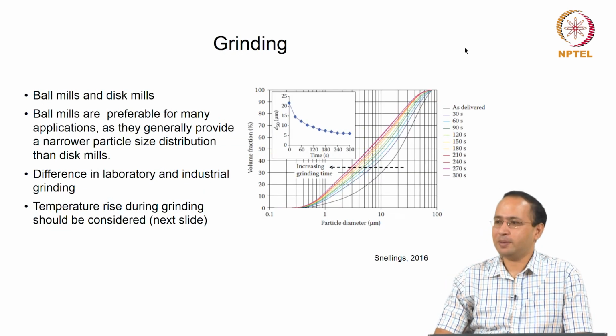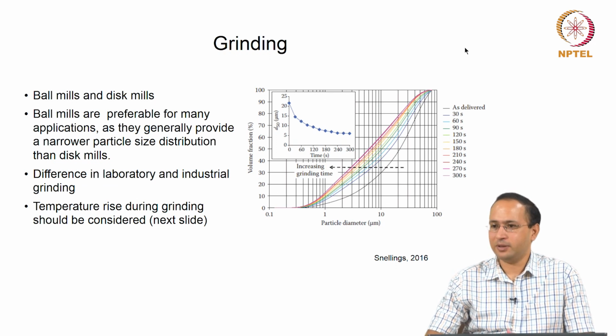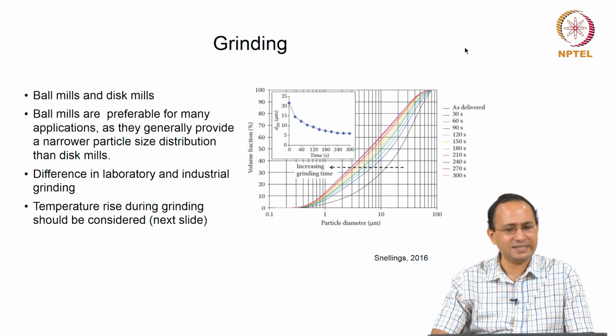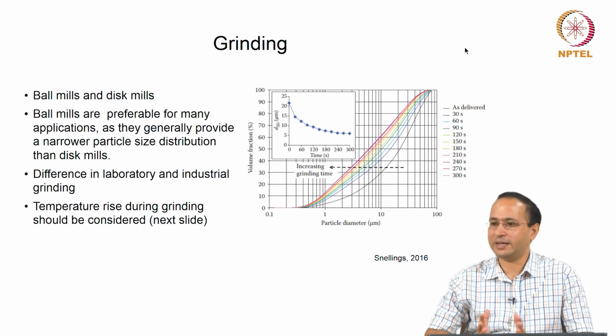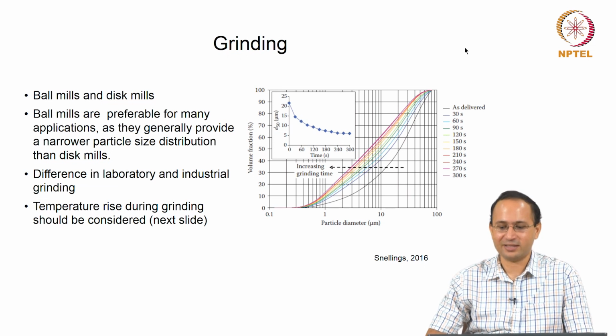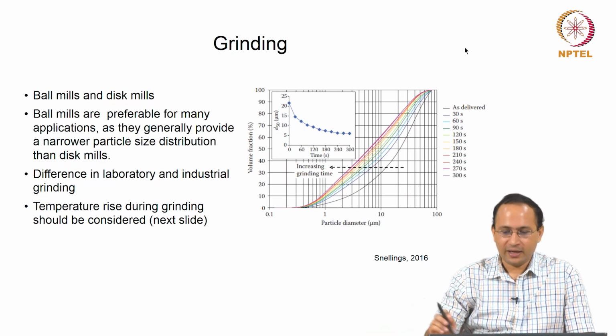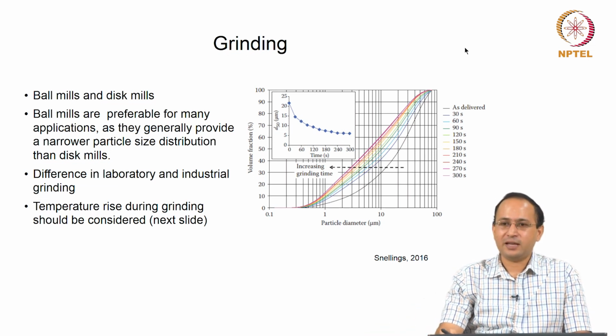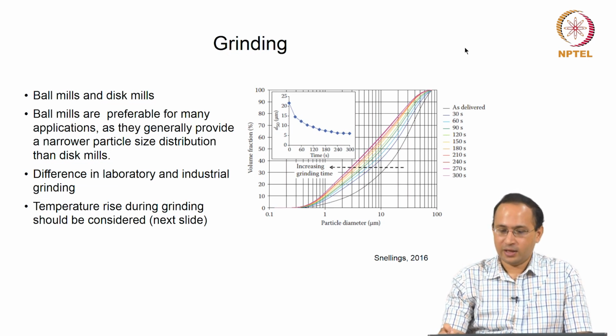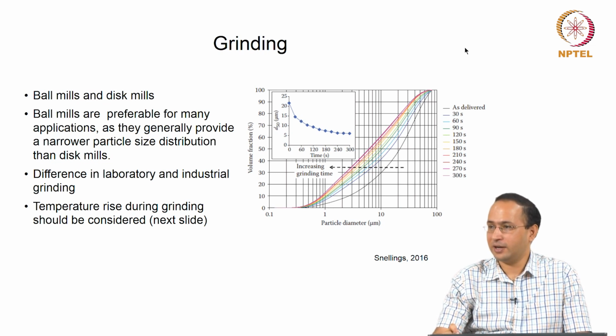What you do after sampling, once you have taken the sample, you have to grind it, right. For grinding we use ball mills, disc mills, different types of mills are available. Ball mills are preferable for many applications as they generally provide a narrower particle size distribution than disc mills, that is a comparison, right. And you have to always keep in mind there is a difference in laboratory and industrial grinding. Industrial grinding may be harsher than laboratory grinding, right.